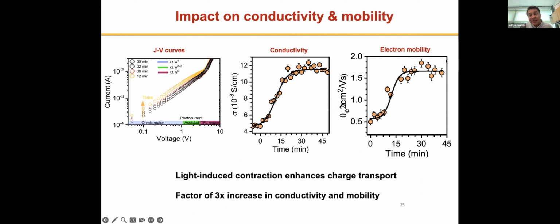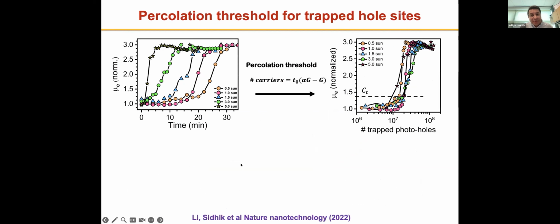And so if you look at the mobility, you see that you get about 3 times increase in your mobility, which over time then saturates. Now, interestingly, there is also a light dependence of this effect, which means that if you increase the photoexcitation density to about 5 suns, you can accelerate this light-induced contraction. You can see that as we go from about half suns to about 5 suns, you can almost instantly get this effect, where you get an increase in your mobility and then you saturate.